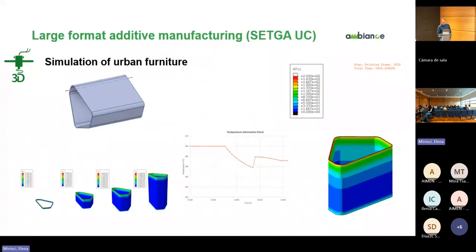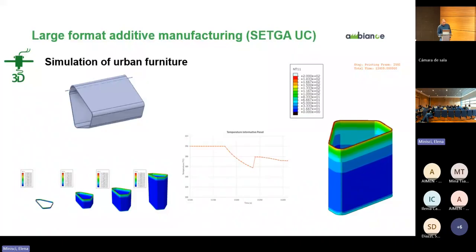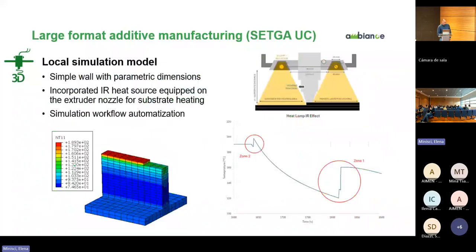Based on what we have seen before, the temperature is different in every point, but mainly governed by the position in the printing direction and by the time, not really by the trajectory. So we have a simplified model that just builds a portion of this wall in height, and in this model we can parameterize all the dimensions, in terms of thickness of the wall, thickness of the layer, and everything related to the printing process, velocities, temperatures, and so on. We also introduced the infrared heating on the top of the filament that is solidary with the nozzle. And then with this type of simulation, we can see the representative curve we are seeing. We can see the new peaks that are because of the infrared heating.